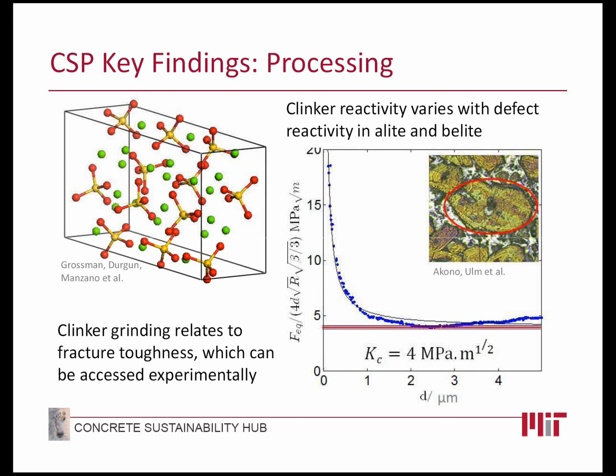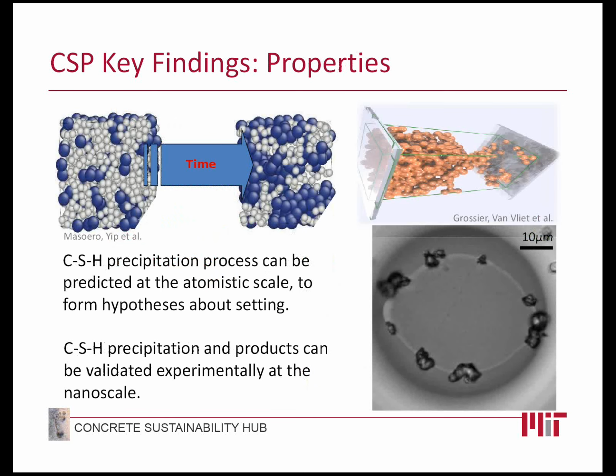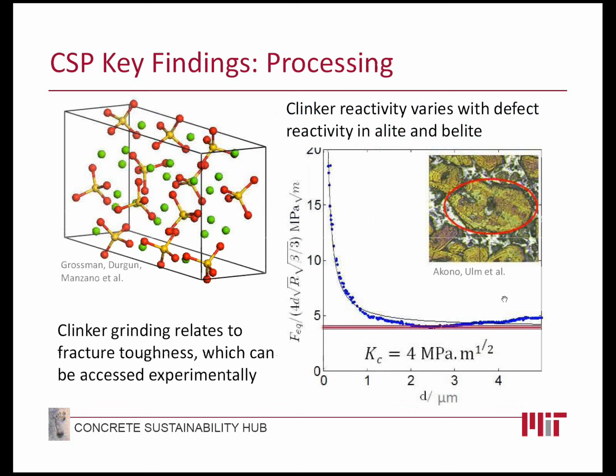On the clinker grinding side, which is also a very energy-intensive part of the process, you can see that we've come, oops, sorry, we're still on that slide. You can see that that is something that is empirically known, that it takes a lot of energy to grind a clinker, but now we actually have a way to measure that experimentally and then see, well, how do substitutional changes in the clinker that might make it reactive make it easier or less easy to actually then achieve the grinding step. So there'll be energetic trade-offs, and we're now in a position to not just predict them through computation, but validate them through experiments that have been developed specifically within the hub. Okay, so next slide, moving from the processing